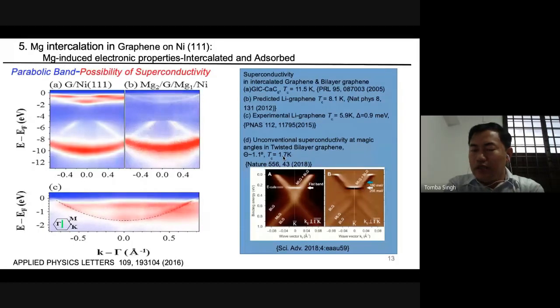If we increase the rotation, then the transition temperature becomes lower, and they observe this phenomenon at specific rotations called the magic angles. The lowest one, 1.1 degrees, has the highest transition temperature, 1.7 K. How does this occur? When we rotate two periodic systems, moiré patterns are observed. These moiré patterns produce their own potential. This moiré potential acts on the graphene system, so it modifies the electronic property. That's why we observe the flat band. The flat band is a signature.